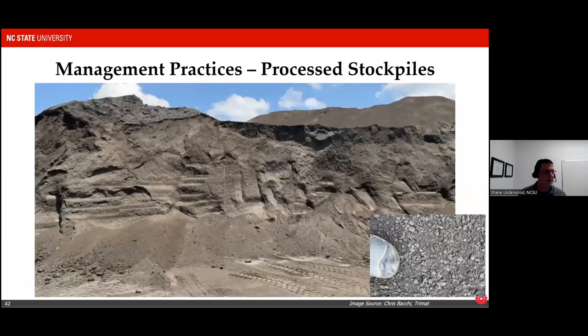Another example, again, we see segregation at the toe. Keep in mind that RAP stockpiles contain asphalt binders, so they can consolidate. It is possible to walk across these stockpiles. They're very rigid. You'll see that in the next slide. And again, we've got aggregate segregated and stuck at the toe of this, which, if incorporated, gives us inconsistencies in how that RAP material will perform.